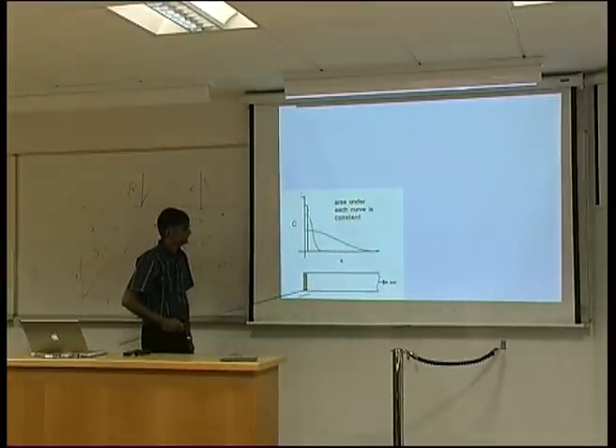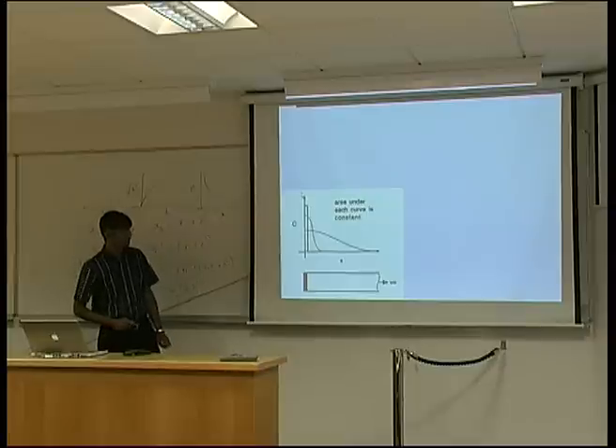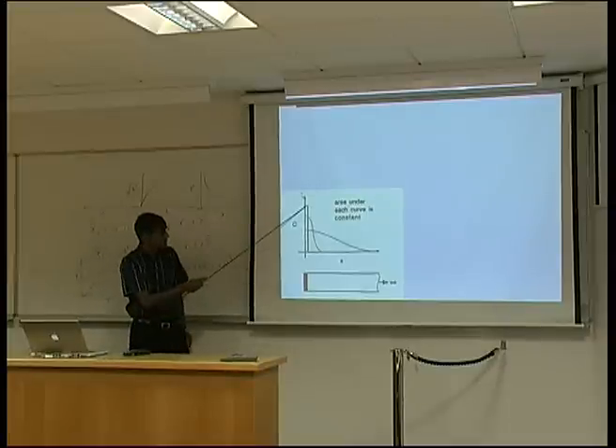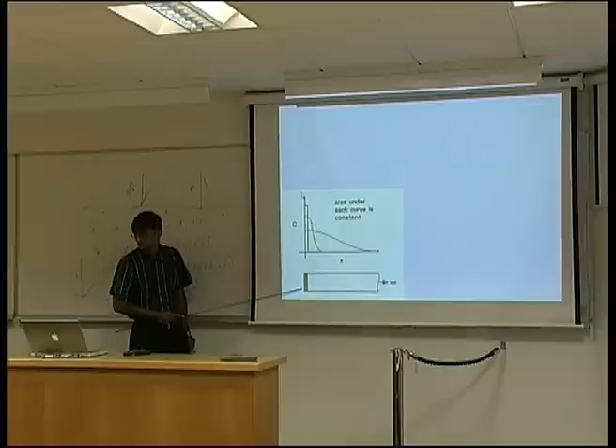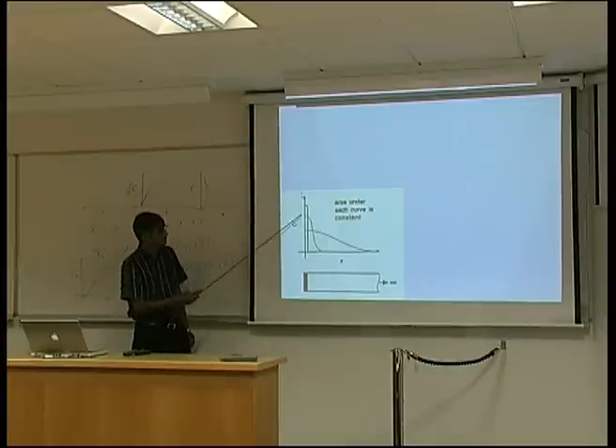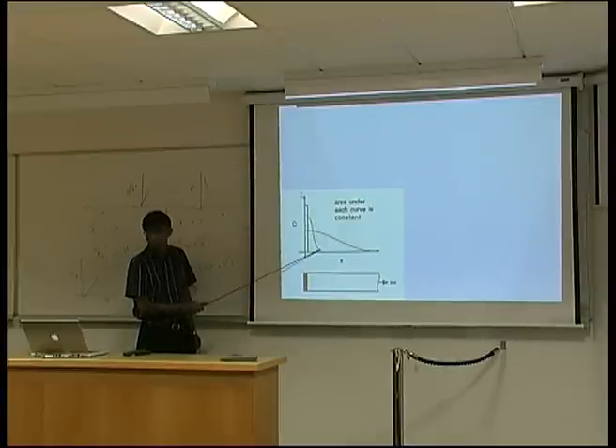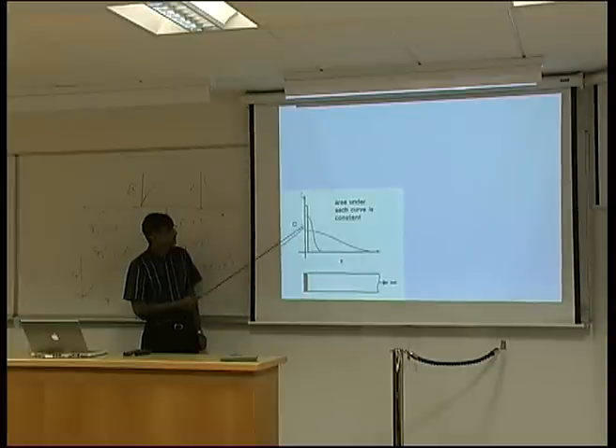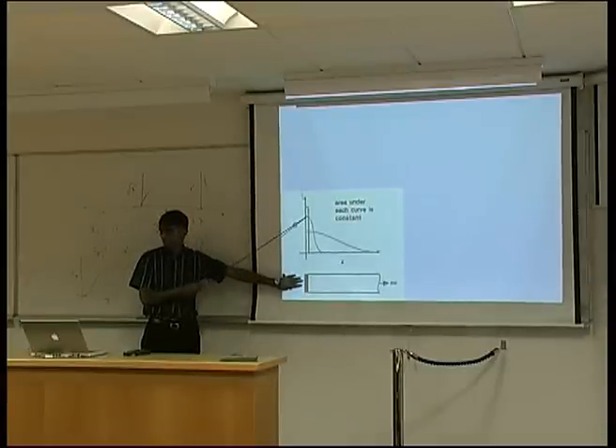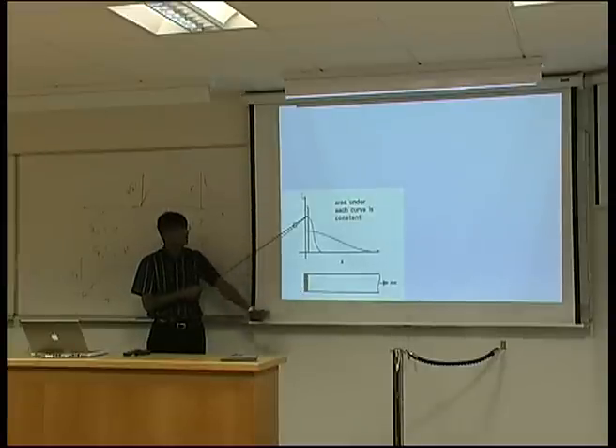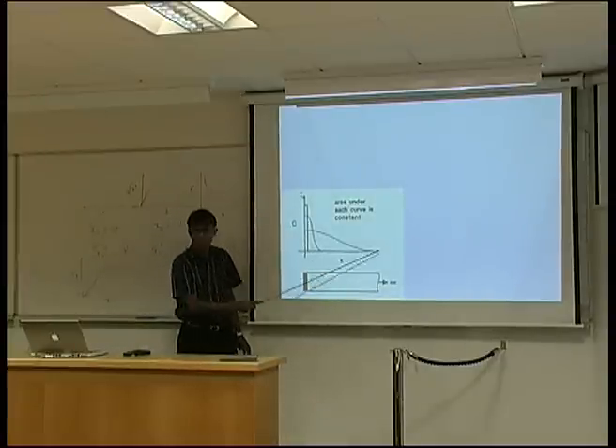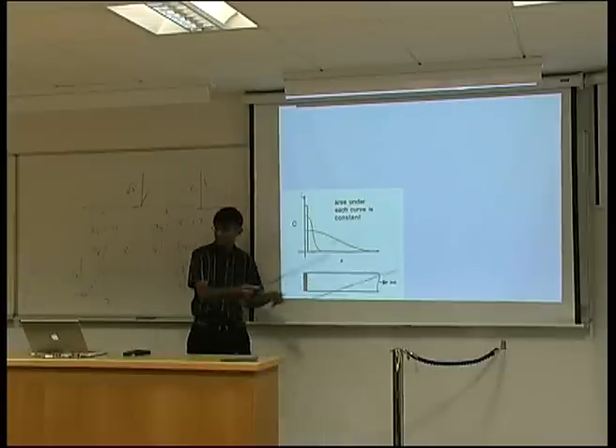If you monitor then the concentration as a function of distance and time, you start off with a thin layer of material, phosphorus, at the surface. As you allow diffusion, it spreads out into the material. Okay? This point here falls because we are not supplying new phosphorus here. We simply put a layer of phosphorus and allow it to diffuse. And as time proceeds, it flattens out further and further and further.